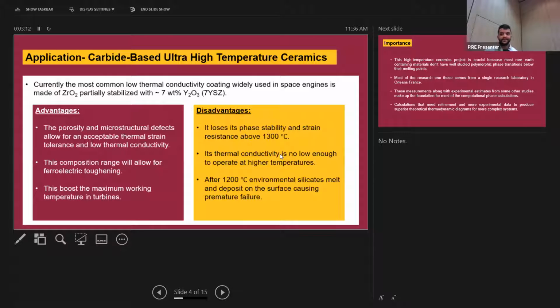And it has some advantages and some disadvantages. The most important advantages of this material are its porosity and the microstructural defects that allow for an acceptable thermal strain tolerance, as well as low thermal conductivity. This composition range also allows for ferroelastic toughening to be active, which means it's very mechanically robust, and hence it's very useful. And this boosted the maximum working temperature of turbines.